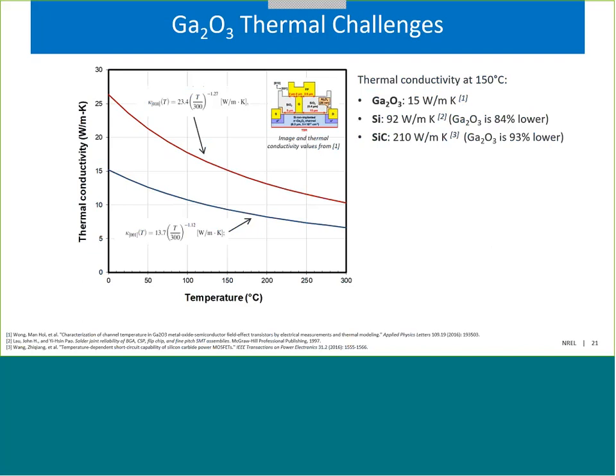When compared at the same temperature of 150 degrees C, gallium oxide has a thermal conductivity that's about 84% lower than silicon and about 93% lower than silicon carbide. And so it's this low thermal conductivity that makes it more difficult to remove the heat from these devices.